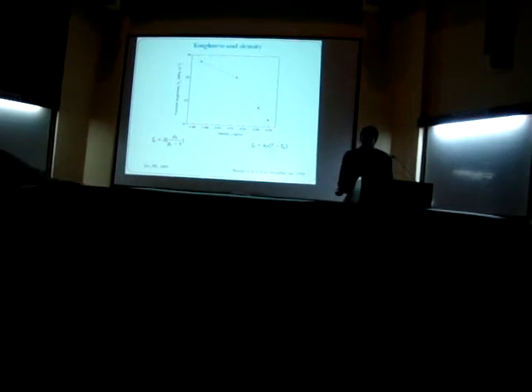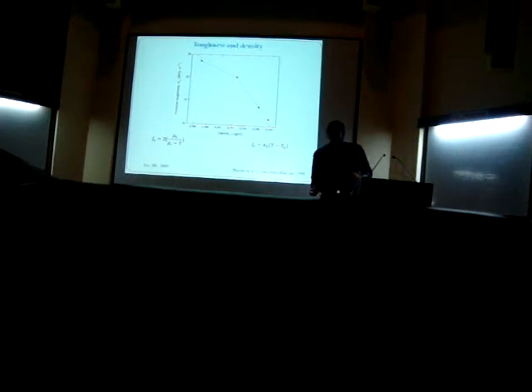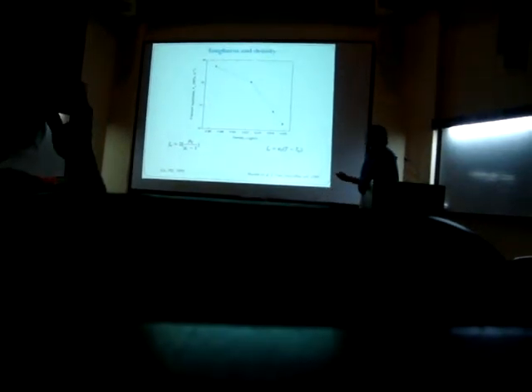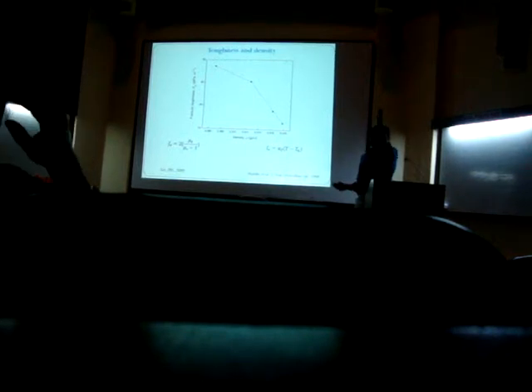The temperature of heating in the above case, like we took it near TG, is called the fictive temperature. That is the temperature of the glass, which has the structure of the glass of the supercooled liquid regime, which has been inherited to the ground state, or the room temperature. So using this, we can also find the free volume. There is a difference in the free volume in the supercooled liquid state and the room temperature state, and using that we can calculate the free volume.